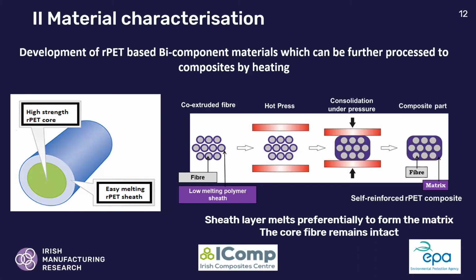So the manufacturing process basically is to take co-extruded fibers or indeed tapes and to melt the outside sheath, which has got a lower melting point than the fiber. That can be done using conventional hot press means, or indeed we have patented a low energy, quick cycle time, radio frequency heating by doping the matrix. Once the matrix is molten, we then consolidate. So in other words, we pack them all together, and in the end it is a consolidated composite material with the fibers taking the load and the matrix imparting all of the other concomitant properties.